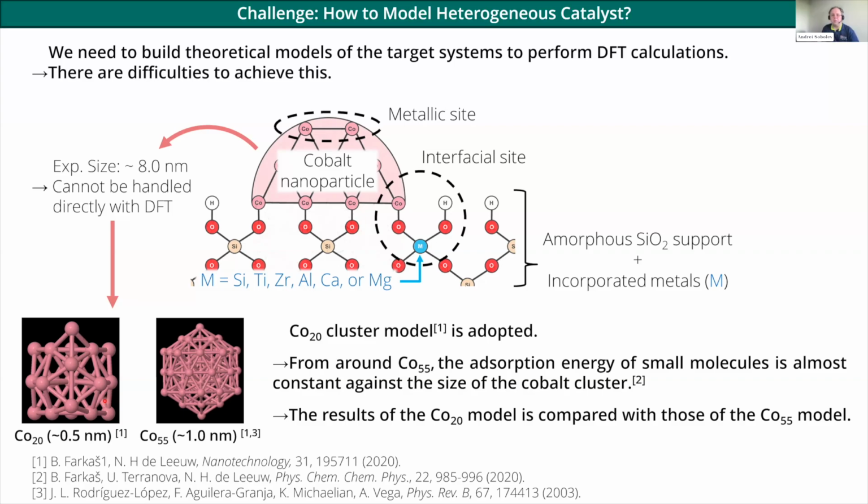Maybe I can add a little bit to that. What we find in general is that the Tkatchenko-Scheffler correction, which was the very first development, somewhat overestimates van der Waals corrections. And at short distances, PBE in fact already has some van der Waals included. So in general, if you want to include van der Waals, one should go beyond Tkatchenko-Scheffler, to many-body dispersion, to have a more realistic description. But for short distances, if you really look at chemisorption, that is not so important for these systems. For other systems, such as layered compounds, of course you should include many-body dispersion. Tkatchenko-Scheffler gives you an idea, but you should really go to the next generation.